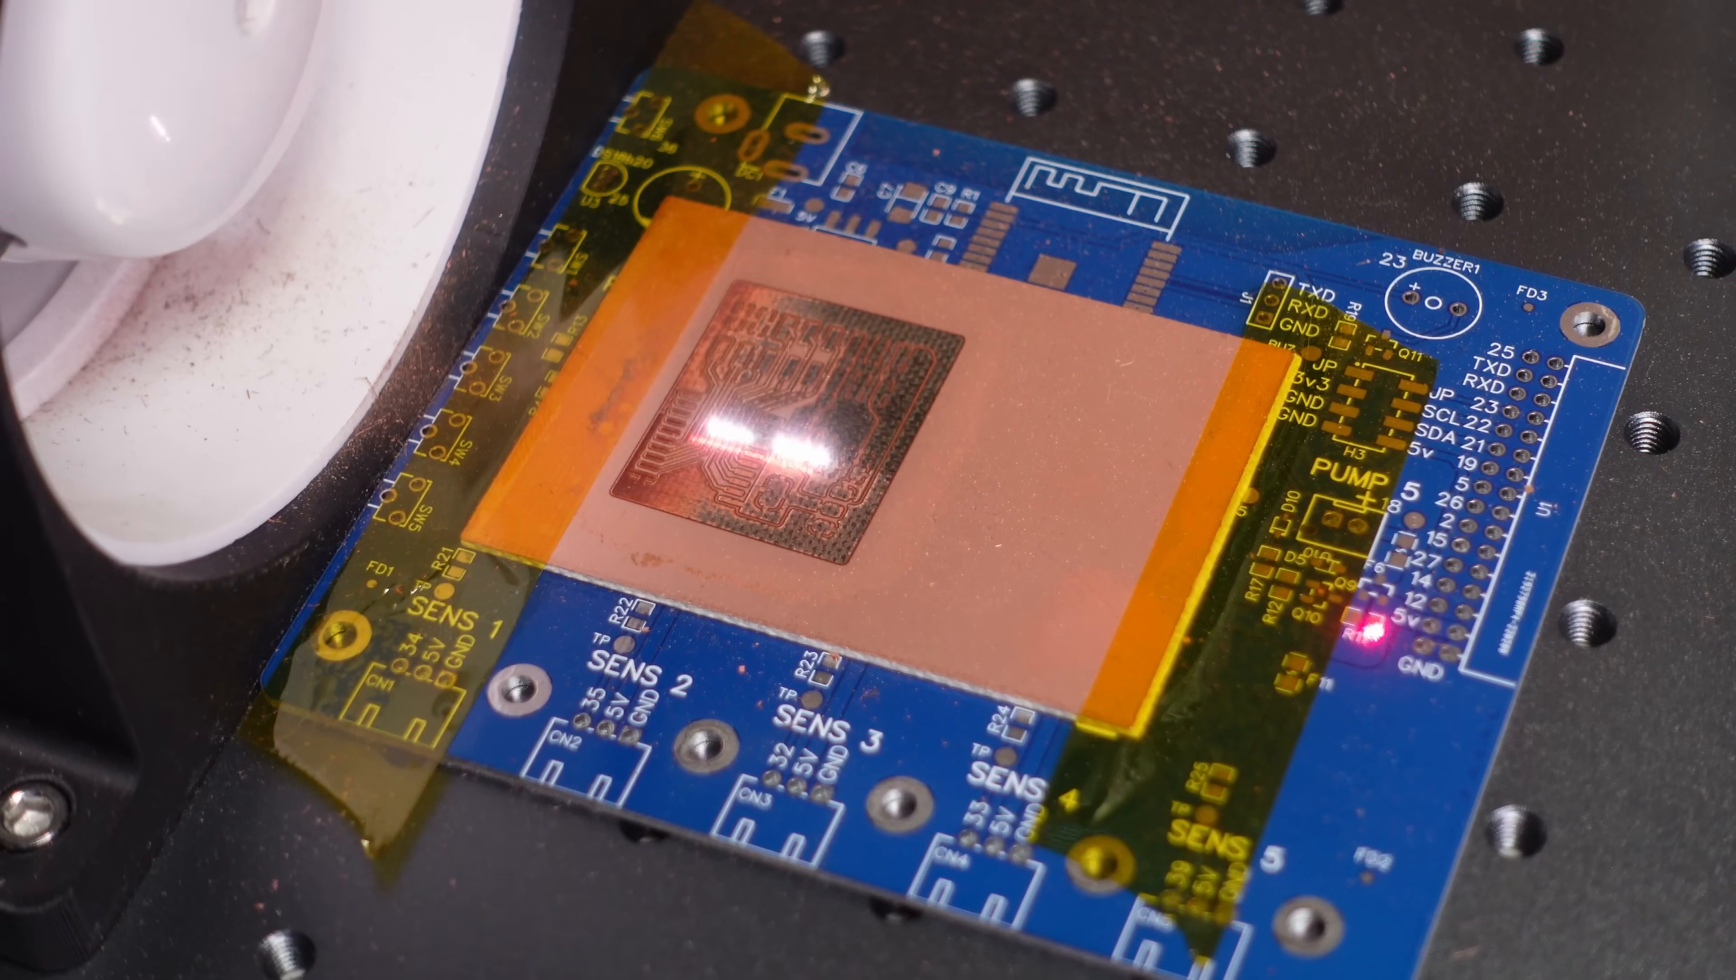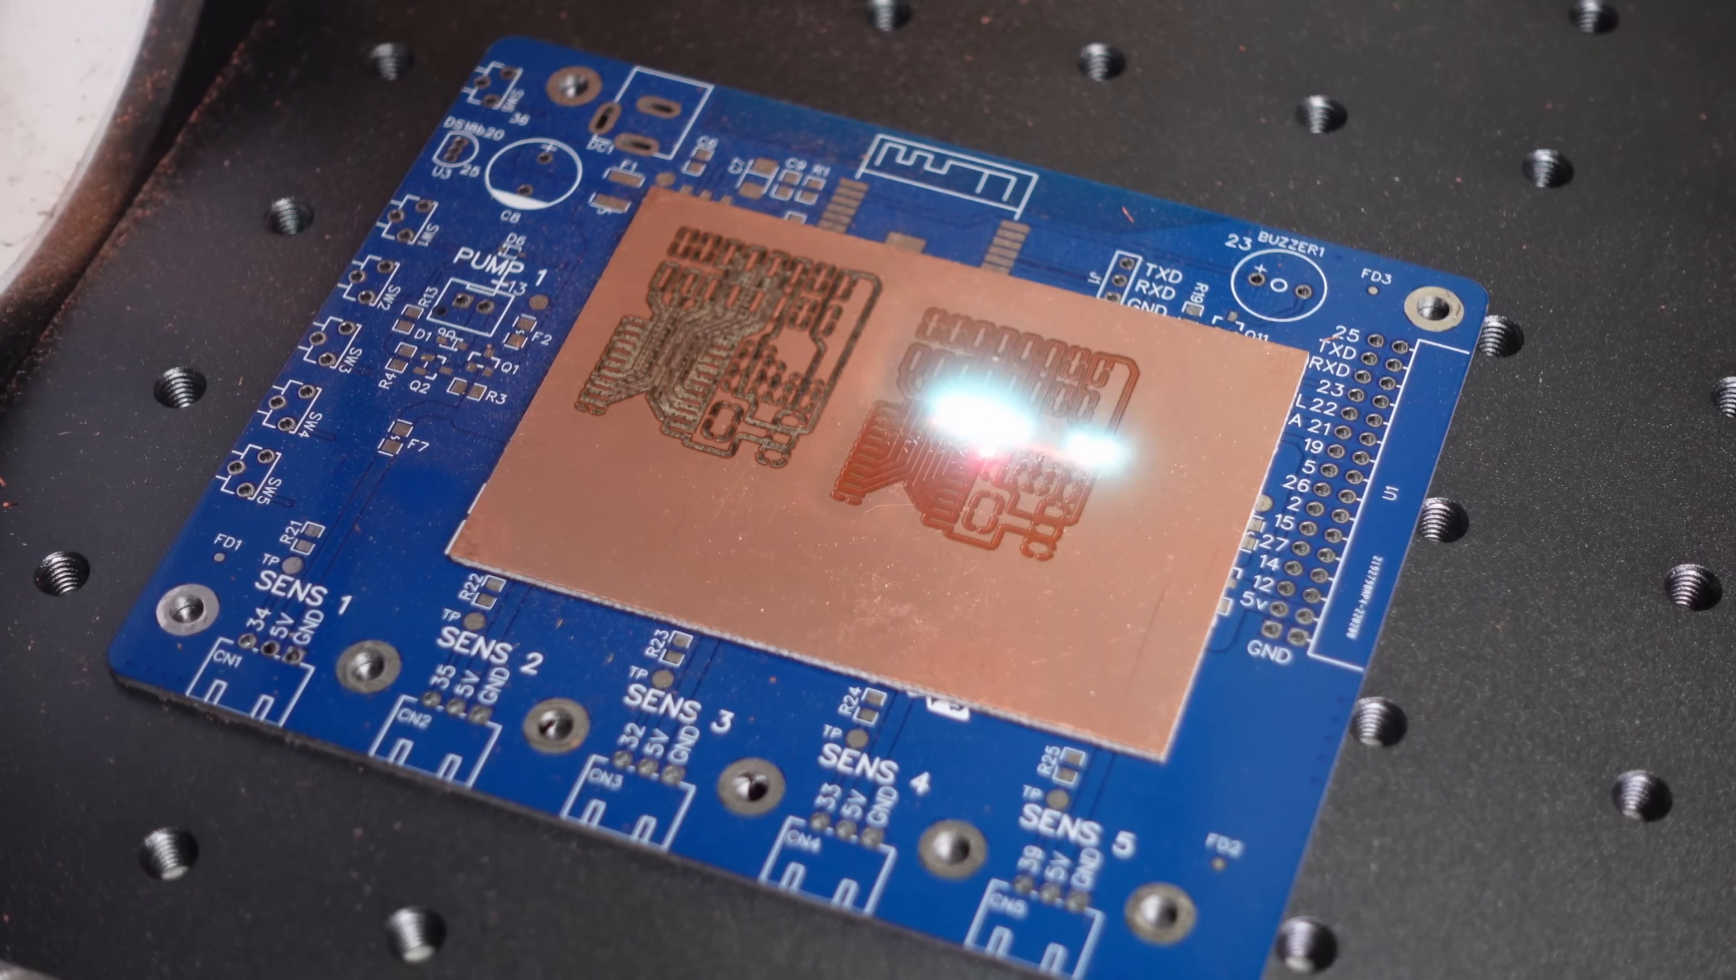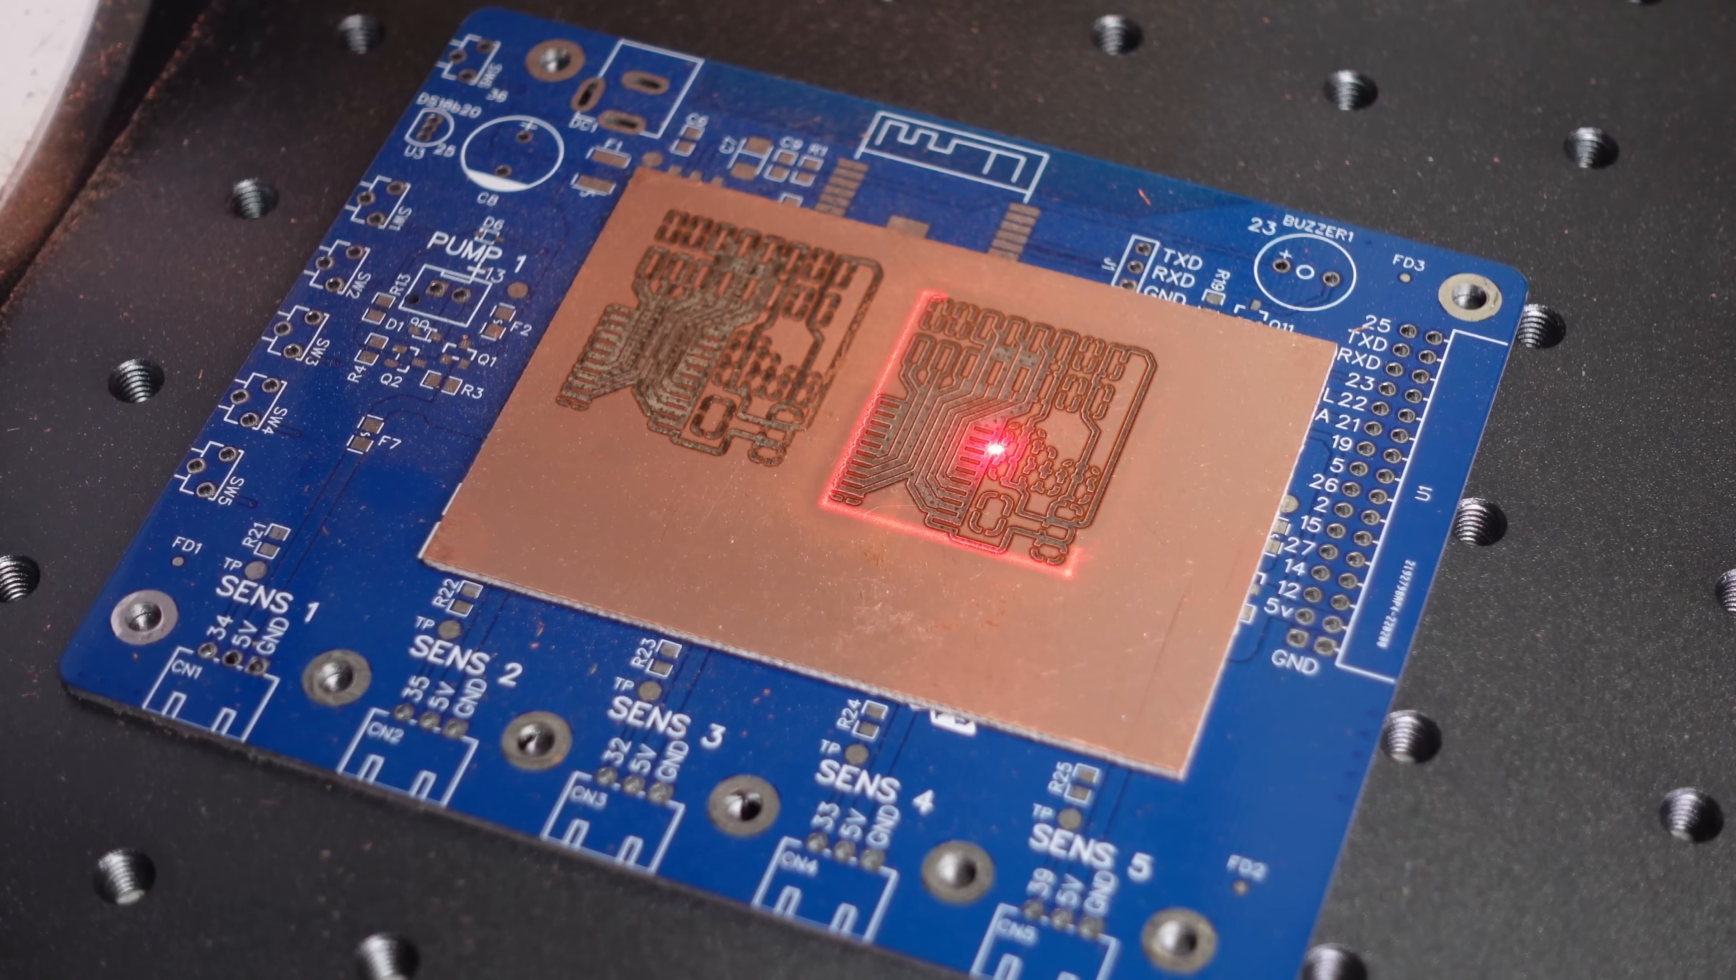The main issue people mention with FR4 and laser engraving is that it tends to burn the substrate, but I believe that's more of a parameter fine-tuning issue. A few YouTubers have mentioned that burning the substrate can even make it conductive. As you can see in my first test on FR4, the substrate turned black, mainly because I did too many passes. In the second test, I carefully adjusted the power and number of passes. I also noticed that it's crucial to position the board so the laser hits it as close to a 90-degree angle as possible. If the angle is off, it tends to remove the substrate beneath the traces. Once everything was properly dialed in, the process took exactly one minute.